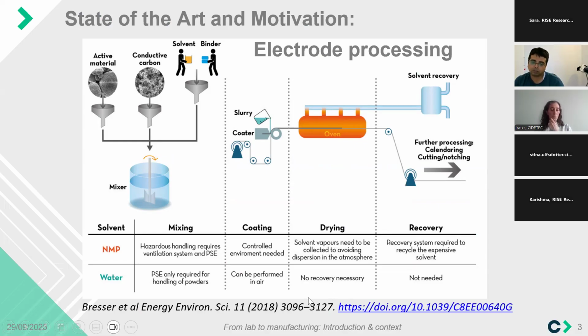On cathode waterborne slurry preparation, mixing, and the coating process, compared to the standard process in which the polymer binder - the standard is PVDF, which is soluble in NMP - but NMP, N-methylpyrrolidone, is a volatile organic compound that, as in NoVOC, we want to get rid of because it has toxicity issues.